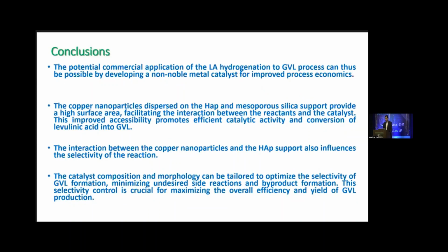So overall, the potential commercial application of the levulinic acid hydrogenation to GVL process can be possible by developing non-noble metal catalysts for improved process economy. The copper nanoparticles dispersed on the hydroxyapatite and mesoporous silica supports provide a high surface area and facilitate the interaction between the reactant and the catalyst, and this improved accessibility promotes efficient catalytic activity and conversion of levulinic acid into GVL. The interaction between the copper nanoparticles and the hydroxyapatite also influences the selectivity of the reaction.